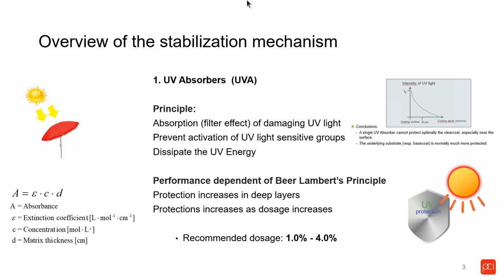Also important about the UV absorber is that the dosage would be different if you are formulating a clear system versus a pigmented system. In a clear system, you don't have any component in your coating formulations that will absorb the UV light and give you some protection from UV. However, if you are formulating a pigmented system, then obviously the pigment or the filler will have some effect of UV absorber, and this will allow you to limit your dosage of the UV absorber.